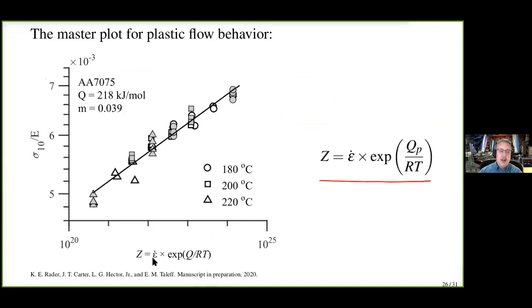Plotting the Zener-Hollomon parameter here on the horizontal axis on a log scale, and on the vertical axis the flow stress at about 0.1 strain divided by the Young's modulus at temperature, we find that all these data come onto a nice straight line, which my little pen won't let me draw. There we go. So through, again, the simple idea of a thermally activated process for flow, we can predict the flow stress as a function of temperature and strain rate. So now we're getting predictive capability for how much force we need to form the part.